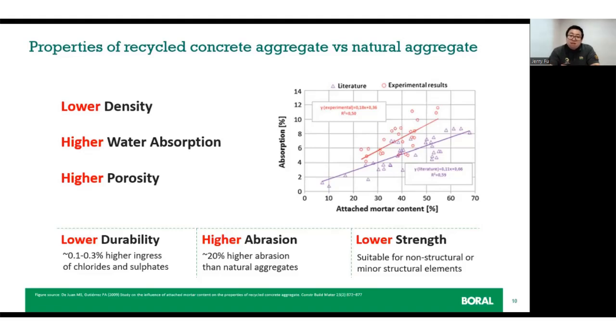The adhered mortar can be lightweight compared to aggregates of the same volume, which causes a decrease in product density. The residual mortar on the recycled aggregate has greater porosity. This allows the aggregate to hold more water in its pores than the natural aggregate. The lower density and high porosity can lead to a reduction in the durability of the final concrete product.